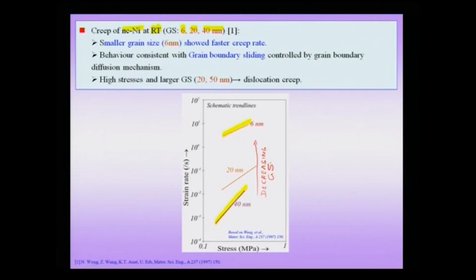Now, what you note is that this is a stress strain rate plot, and for a given stress and for a given testing time, you notice that the strain rate increased with decrease in grain size. The smaller grain size sample, the 6 nanometer sample, shows a faster creep rate, and this behavior was attributed to grain boundary sliding, which is of course accommodated by certain diffusion mechanism.